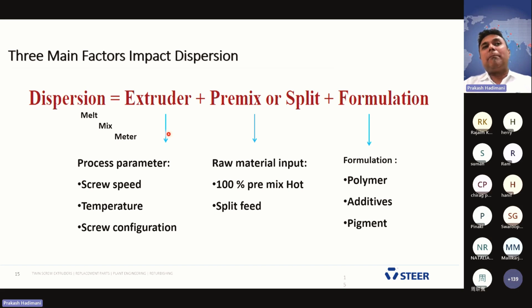Three main factors impact the dispersion. If someone says, okay, I'm not getting a good dispersion, there are many reasons you're not getting the dispersion. Maybe your pigment has agglomerated particles. To break that and get the dispersion, you need to add waxes and you need a compatibilizer. Then only can you get better dispersion. To get the dispersion, you need an extruder, a twin screw extruder. In the twin screw extruder, you need to have a screw speed. Sometimes the higher the screw speed, the better the dispersion. It depends on the nature of the pigment.